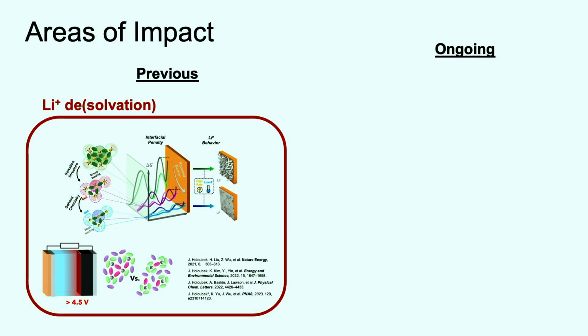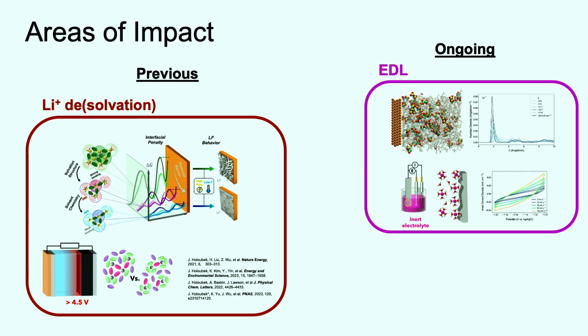So my previous PhD work, this is everything that I have done and hope to do in one slide. We looked at how this liquid interface behaves under kinetic strain. What I mean by kinetic strain is fast charging or extreme temperatures, and thermodynamic strain. In this case, I mean very high voltages. We were able to show some things, found that this kind of hybrid computational experimental approach is quite useful in understanding this region of space.